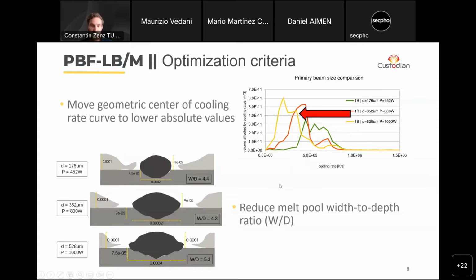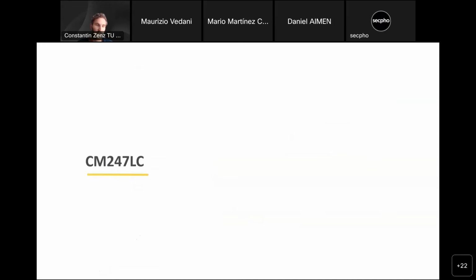And the other thing that we're closely looking at in the simulation is the width to depth ratio of the melt pool. On the lower left here, you can see these 3 simulations, just different beam sizes, and we can see how the penetration depth of the substrate stays approximately the same, but the width gets larger, and the lower the width to depth ratio, the better in terms of hot cracking. So these are the 2 criteria which we're looking at when we try out different beam shapes to find an optimum.